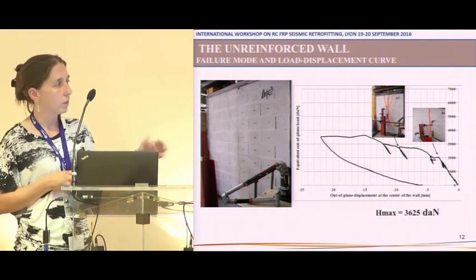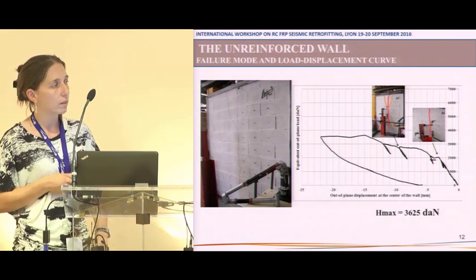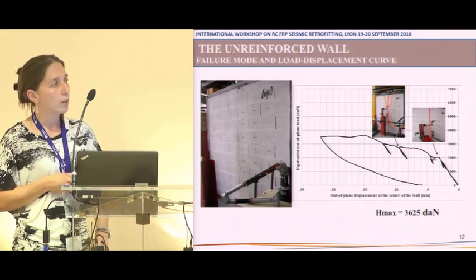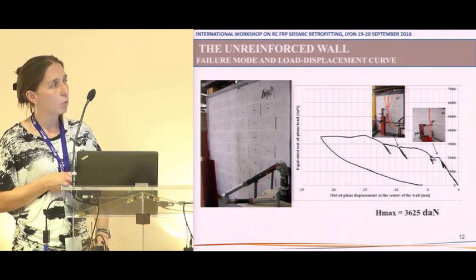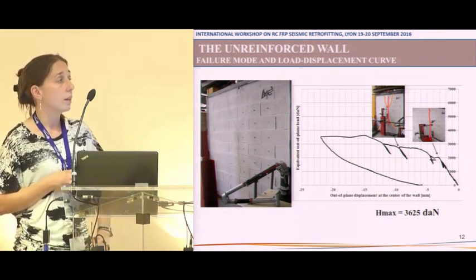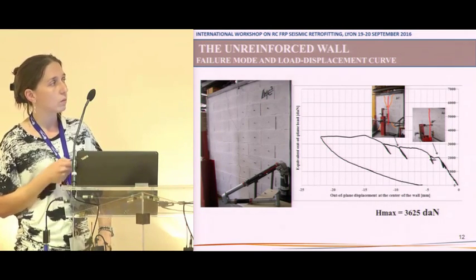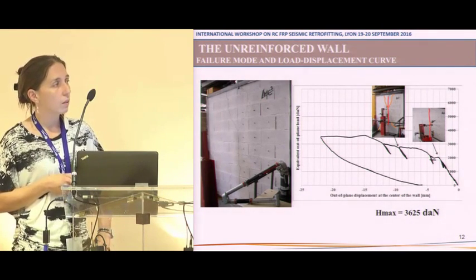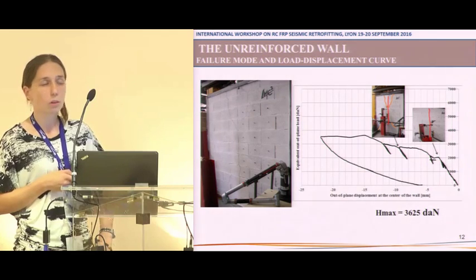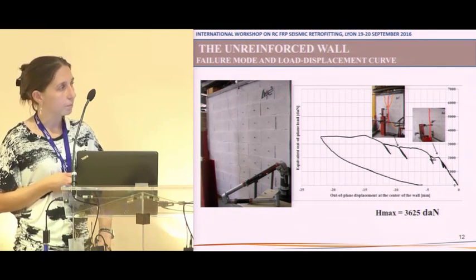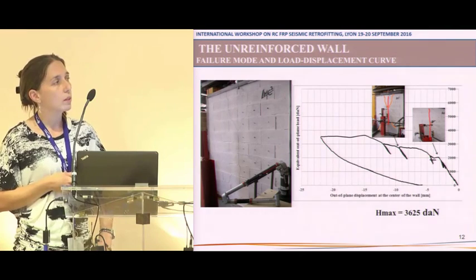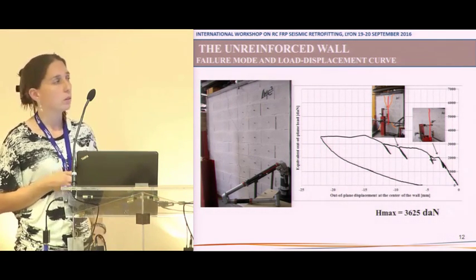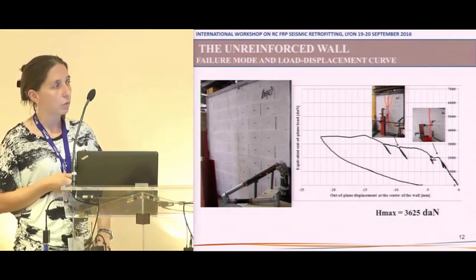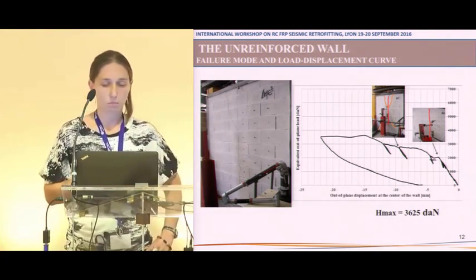Later in the loading, inclined cracks form, two directed along the lower corners, and on the upper sides we have inclined cracks with a lower inclination. The failure mode is symmetrical, which is a good thing for our setup. Once the cracks appear, their opening increases with the load and the displacement.